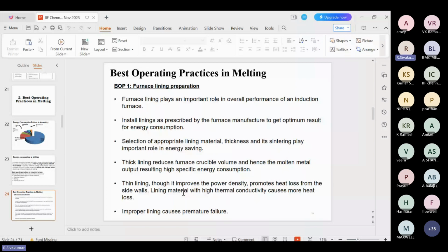So the lining is very, very important. A thick lining reduces the crucible volume and hence the molten metal output, which leads to high energy consumption. A thin lining, though it improves the power density, promotes heat loss from the sidewalls. Lining material with high thermal conductivity causes more heat loss. Improper lining causes premature failure. So the furnace lining is very, very important.